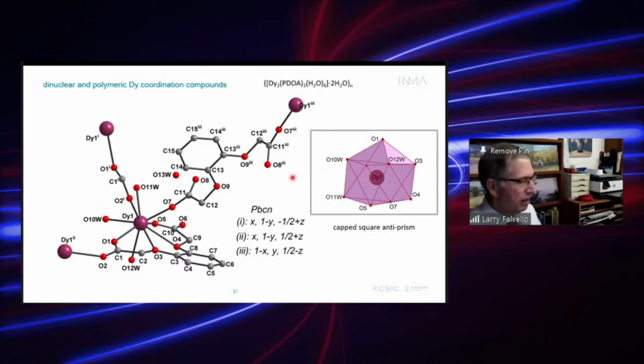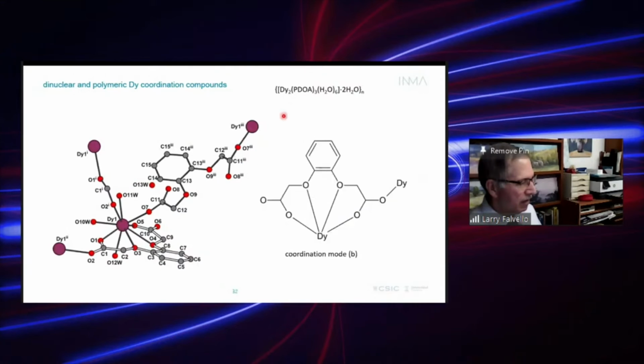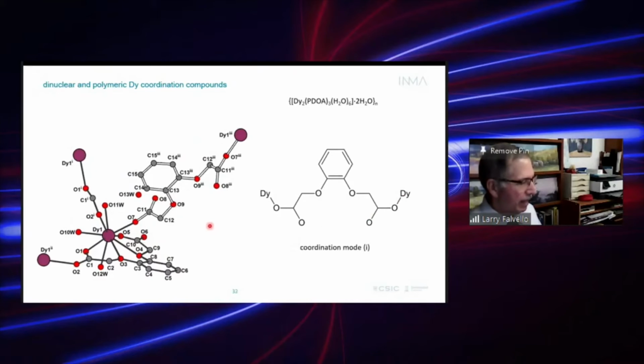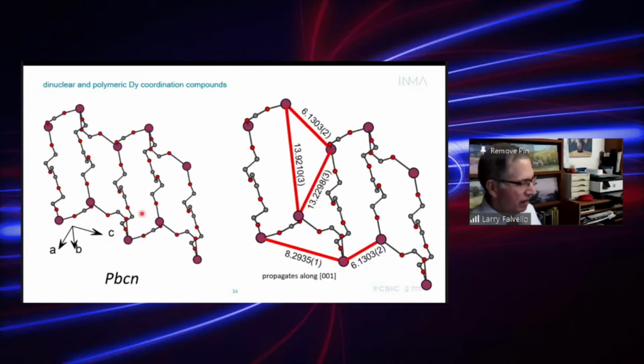square antiprism. And we can see here that the PDOA ligand attaches in 2 different ways. One has a trichelate and also bridges through a short bridge to another dysprosium, and one is a long extended bridge to another dysprosium atom. All the dysprosium atoms are related by symmetry. Well, the first one has one of these coordination modes that we saw in the previous slide, with three chelates and then the other dysprosium, right? Okay. And the long bridge has the arms extended mode, bridging 2 dysprosium atoms. And the result of this is this staircase-like structure, right?